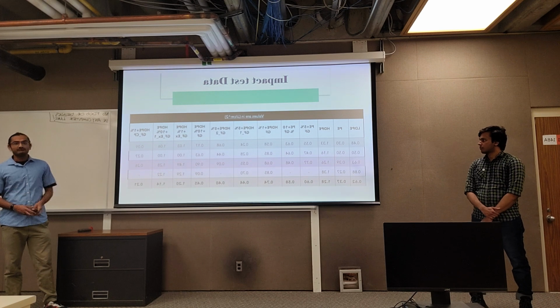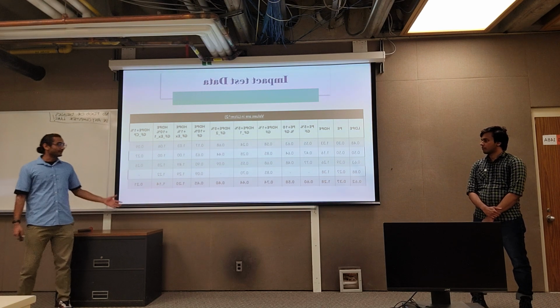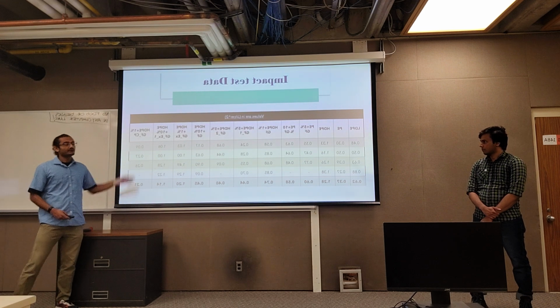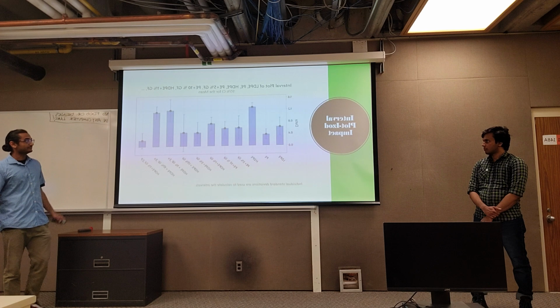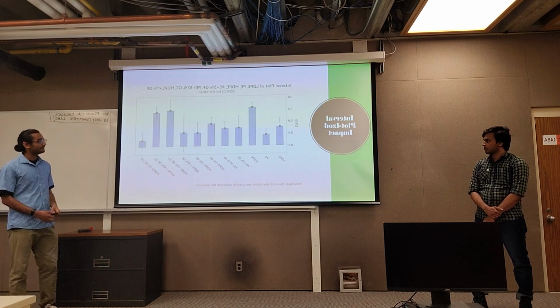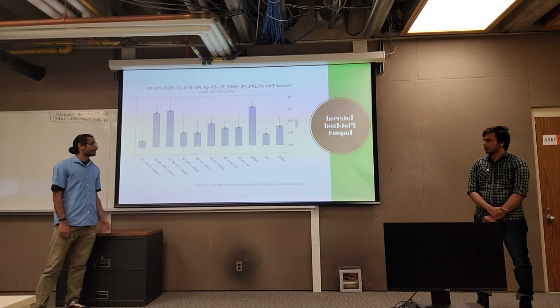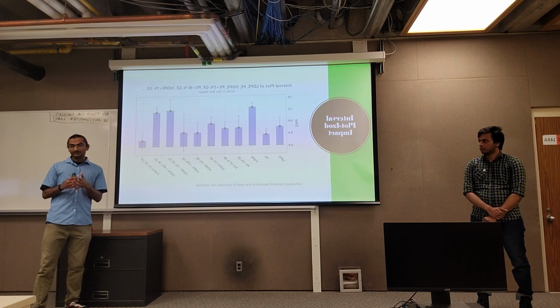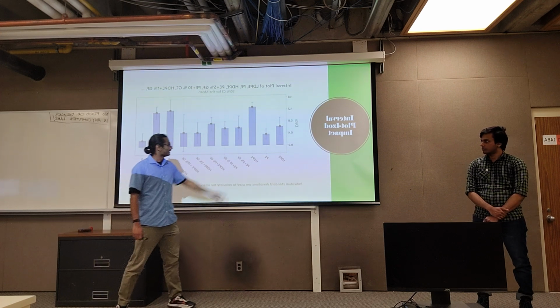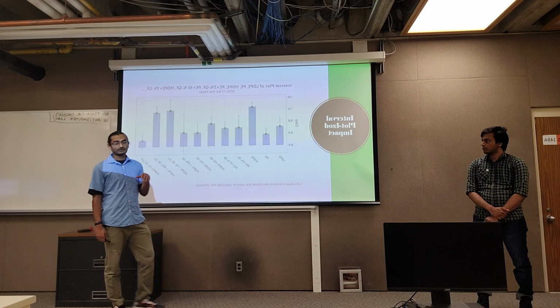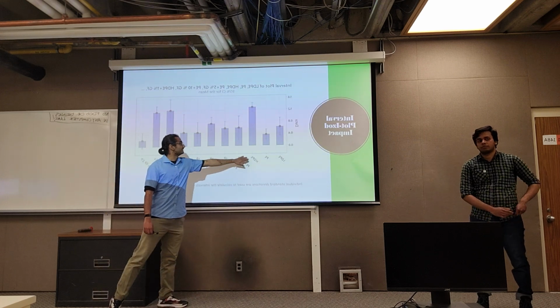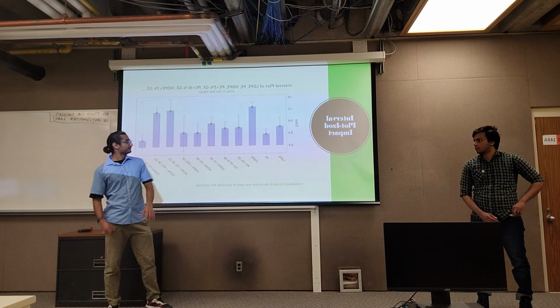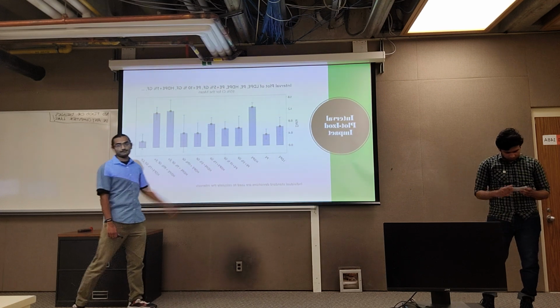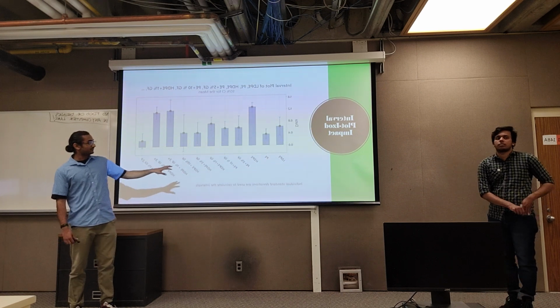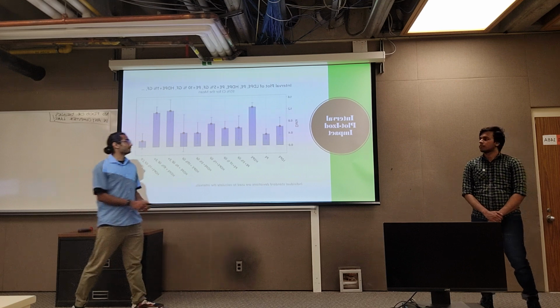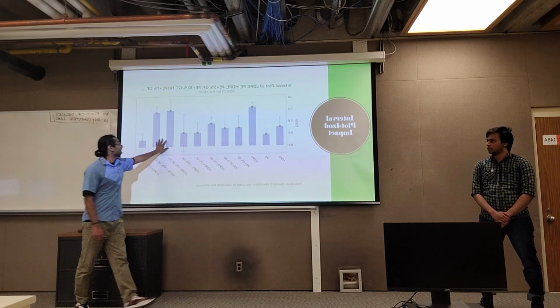These are the Izod data we conducted in duplicates and quadruplets, and the mean values we got are here. Doing the graphical interval plot of this, we got the sample data this way, where we were able to see that by the method of compression molding in the HDPE, we got a decrease in the impact strength results. As you can see, here it's higher, and with the addition of reinforcement, there was a subsequent decrement. With the extrusion, we got fairly similar results when compared to HDPE here and the extruded results over here.